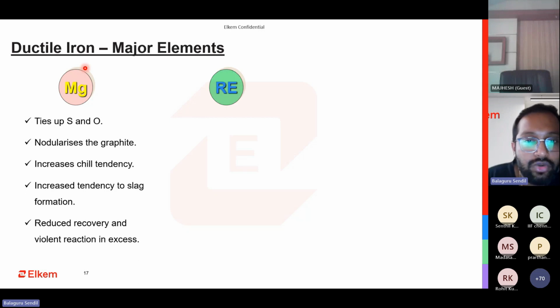And the next one most commonly present is rare earth. Rare earth is cerium and lanthanum, which is commonly present in your magnesium. It also acts as an element which helps you with nodularization. We have seen it earlier. If you're trying to use cerium alone to make ductile iron, it is possible, but it takes a lot of process control, and cerium is not as abundantly available. But pure mischmetal is available, which is a combination of cerium and lanthanum. We can use that. Using that 100% instead of magnesium is a challenge. It's not very commercially viable.